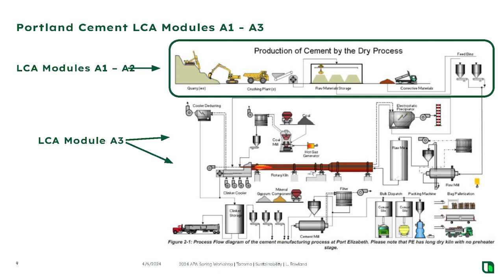Then finally, I take that clinker, I cool it, I grind it up real fine to make cement out of it, and I store it. That's my cradle to my gate. My gate for cement is in the silo, ready to put in your truck to ship to you. In precast, the cement makes up about 75% of your carbon footprint associated with a mix. With a precast concrete mix, the green bar there is 75% is from me. I'm the cement guy, I bring the carbon to the party, right? That's my cross to bear. So that's why I need to improve my act and get better at reducing my CO2.